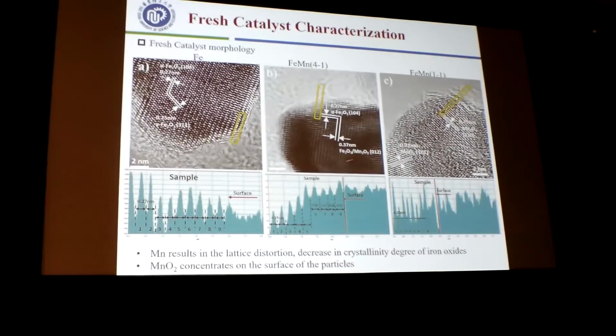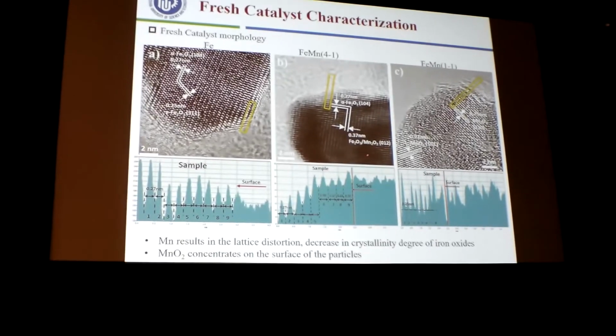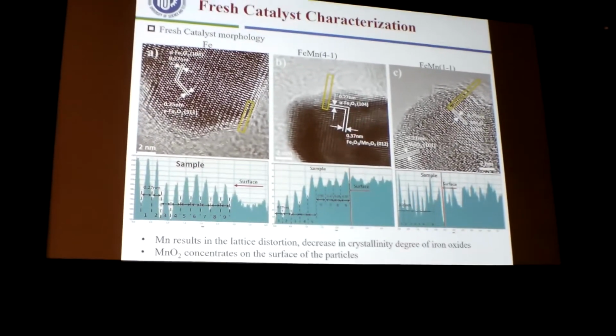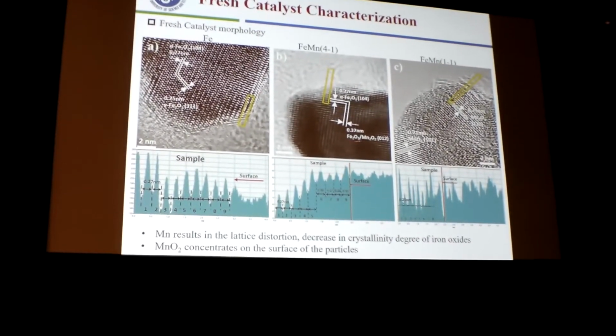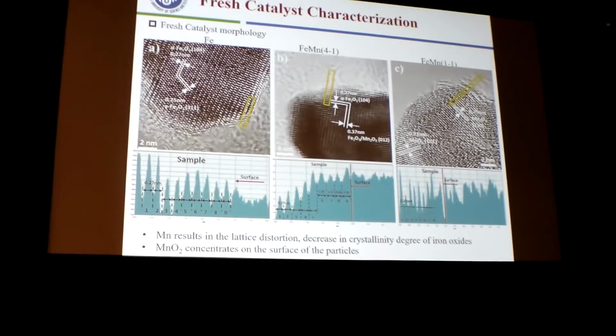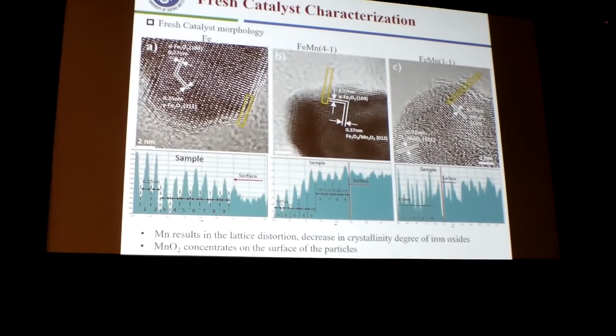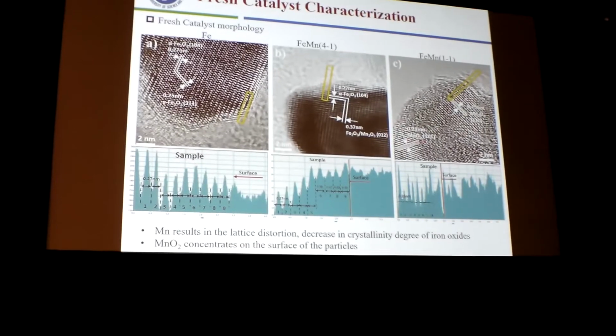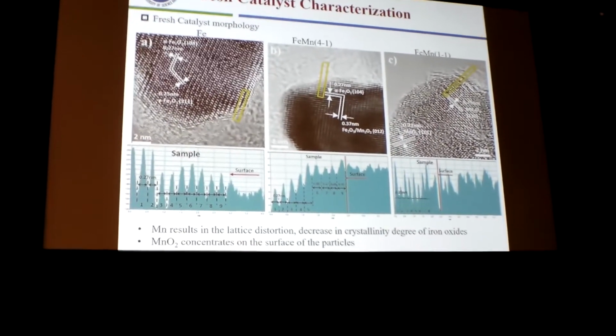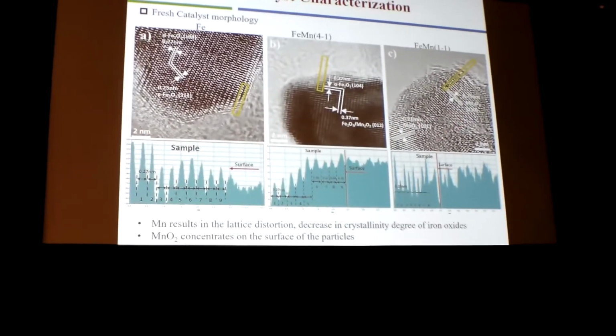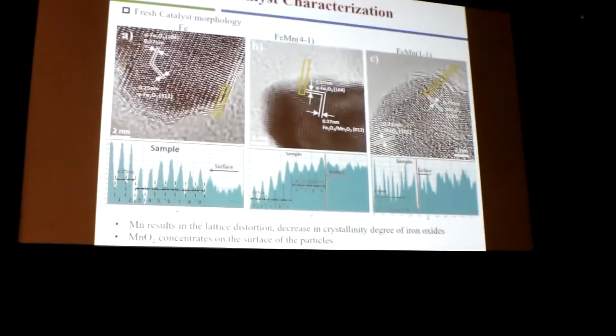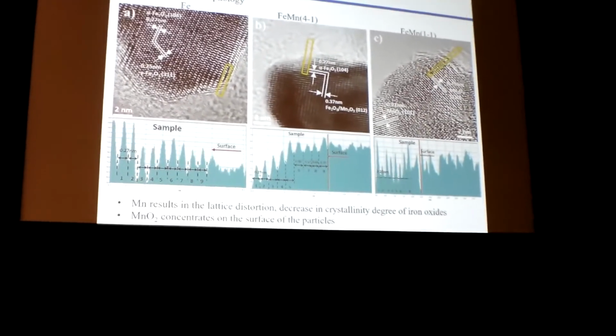Instead, we observed the mixing phase of iron oxide and manganese oxides. And as we further increase the loading of the manganese to 1 to 1, the lattice distortion was observed. And actually we also observed the concentration of the manganese oxide phases.